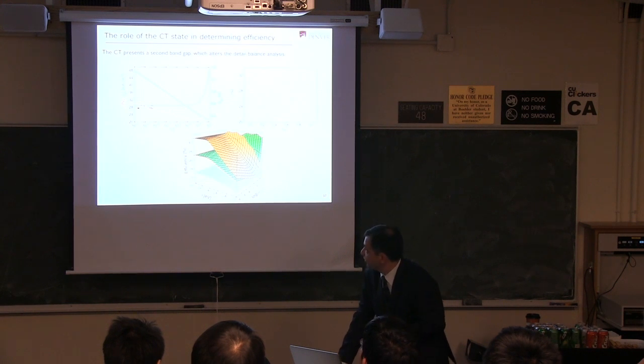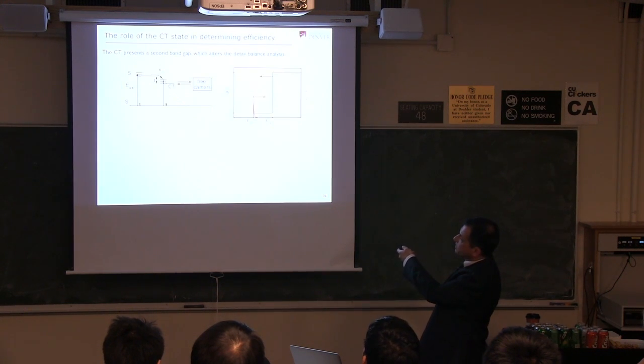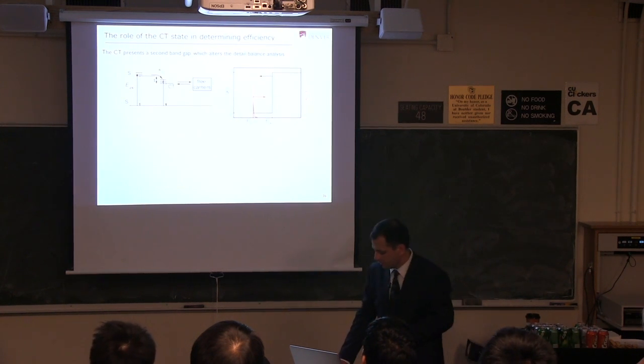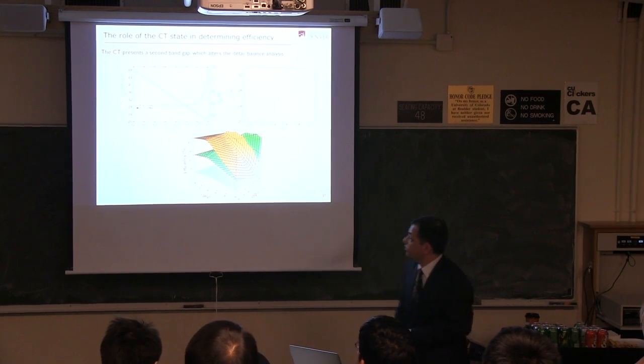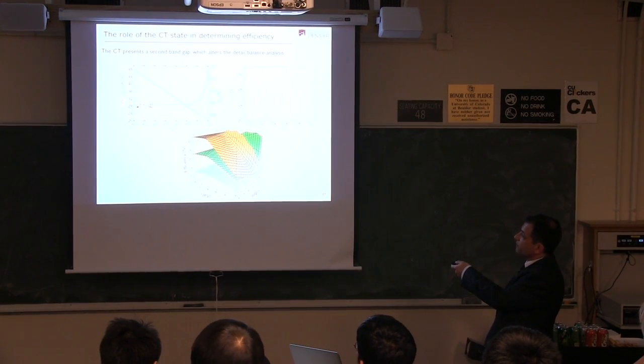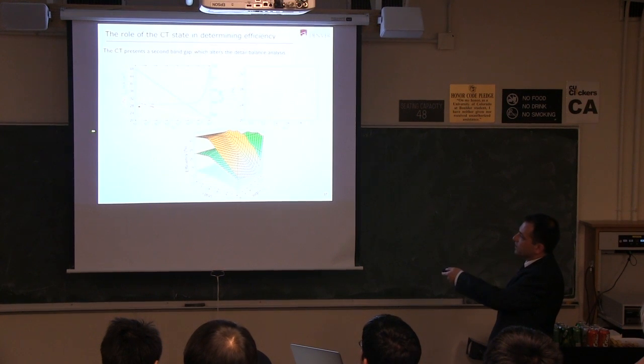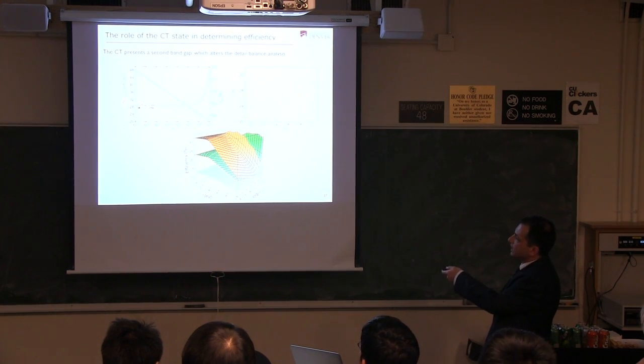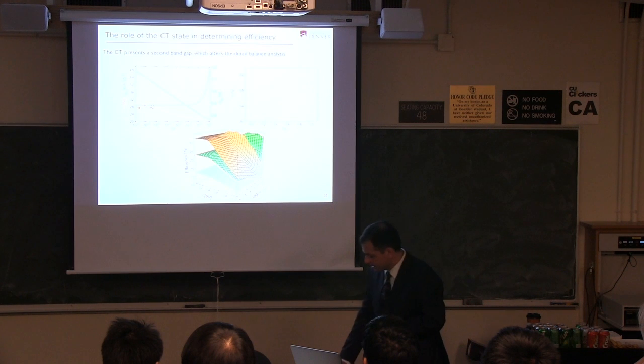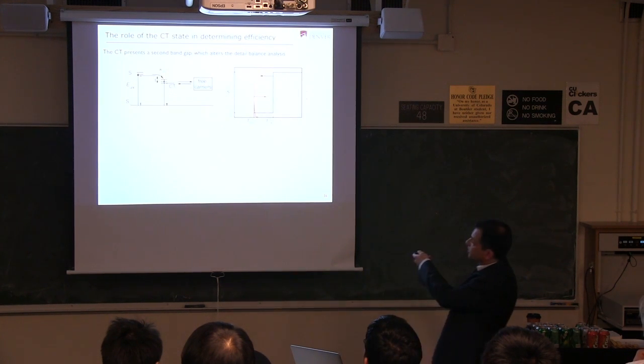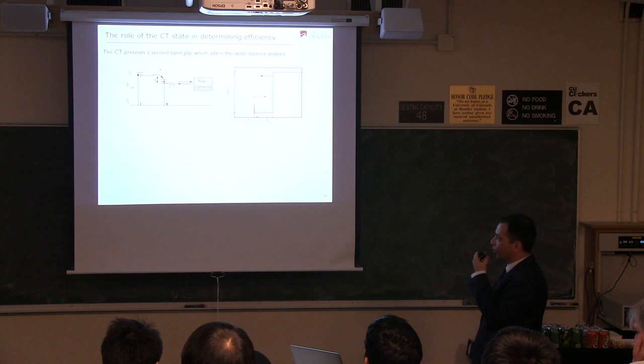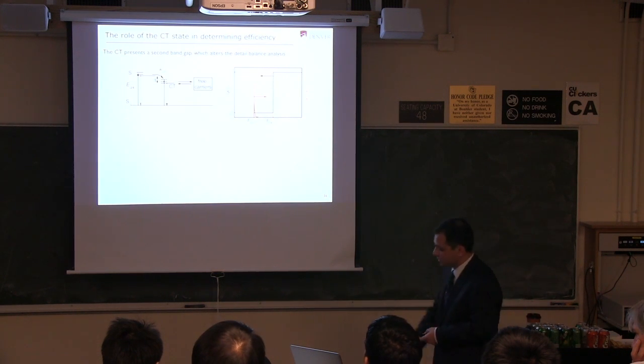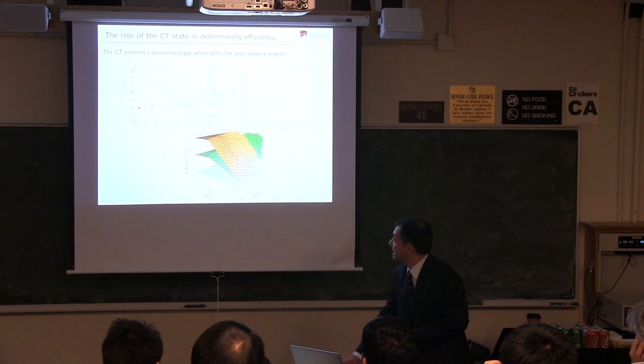Well, the free parameter here is the strength of the absorption of the charge transfer state. We'll call that alpha CT, absorption of the charge transfer state. So if you plot, for instance, the efficiency of the device in red versus alpha CT, what you see is that when you increase alpha CT, it declines, and then there's a minimum and it goes back up. So what's happening? Initially you have a little bit of absorption of this alpha CT state, which is re-emitted at a lower band gap. That's a loss mechanism. So as you first kick on alpha CT, you get a loss.